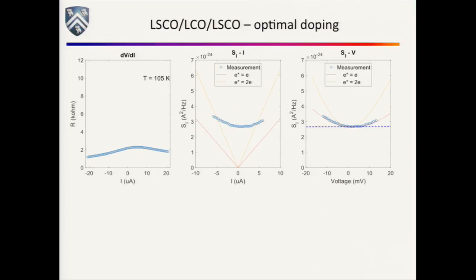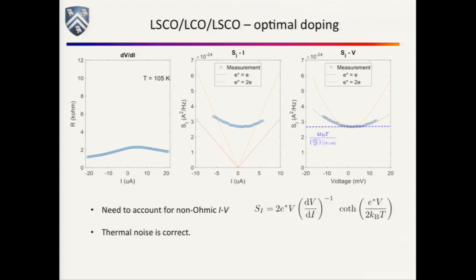I should point out, it's a little hard to see, the lower thin red curve is using this expression. If I assume that the effective charge is just one electron, it looks pretty nice. This would be if the effective charge was two electrons. I should also point out that the reason I'm showing this plot versus the voltage is that at zero bias, the thermal noise is correct. You really do get the temperature.